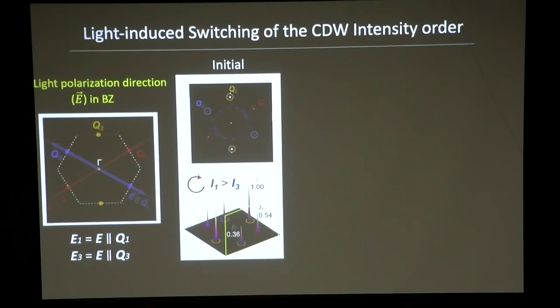Our original intent was to try and manipulate this charge density wave pattern, high, low, least, high, using circularly polarized light. That actually did not work. And so my student and my postdocs decided to try linearly polarized light. And so I'm going to show you data on what happens when you shine linearly polarized light. So we're able to take light and point the electric field along these three different CDW directions.